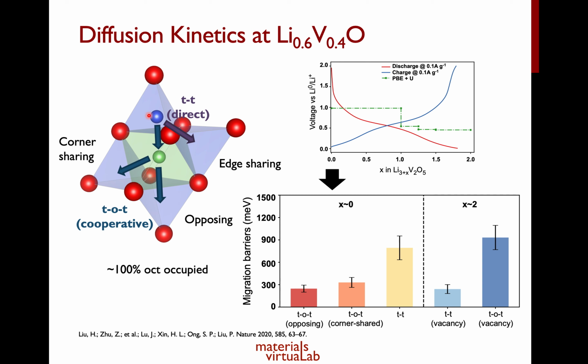Now we are inserting lithium into a tetrahedral site when we first insert lithium. So there are a few potential diffusion pathways for lithium. One possible pathway is that you have this lithium in the tetrahedral site and you just hop directly into a neighboring tetrahedral site. Now this requires the lithium to pass through this oxygen face, which is actually neighboring two fully occupied octahedrals.